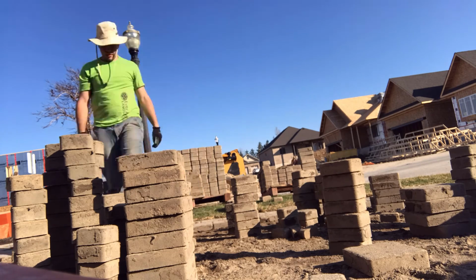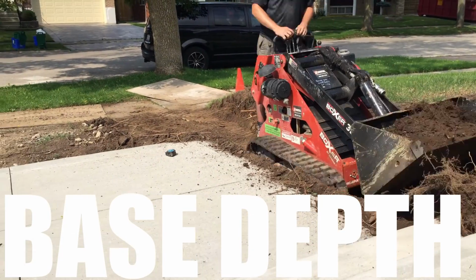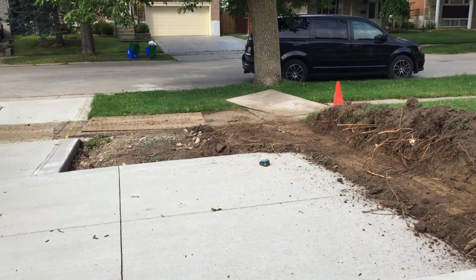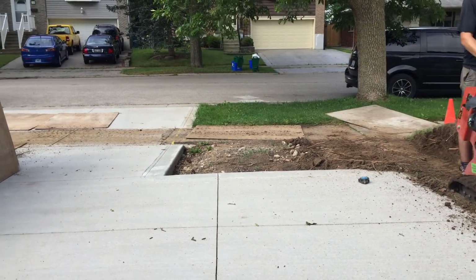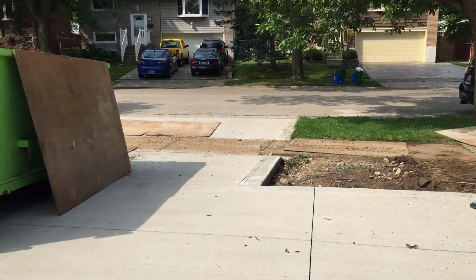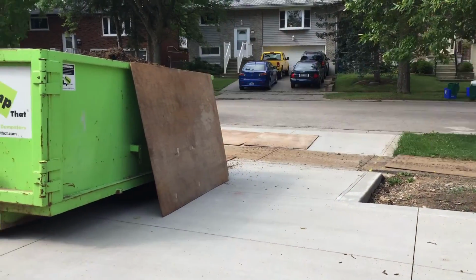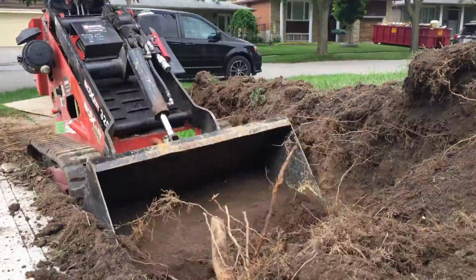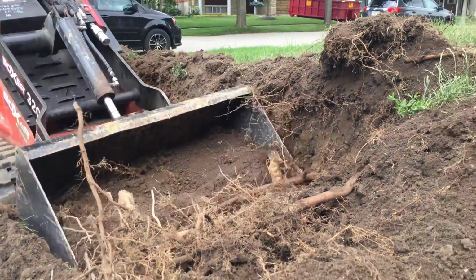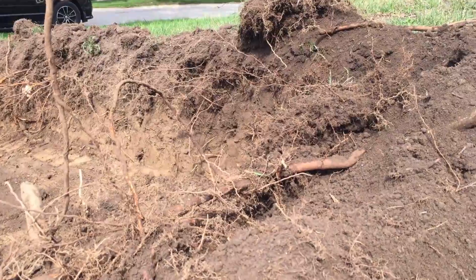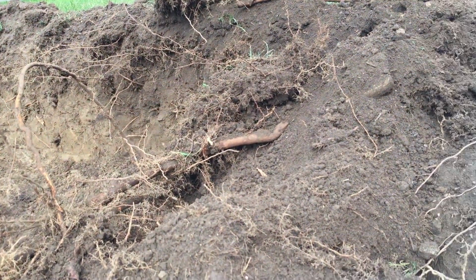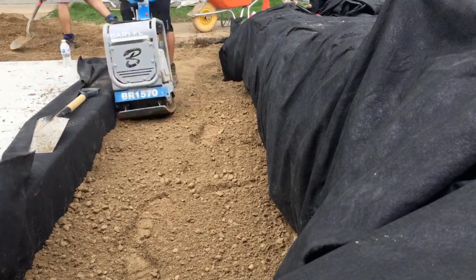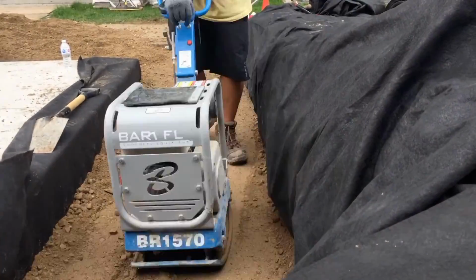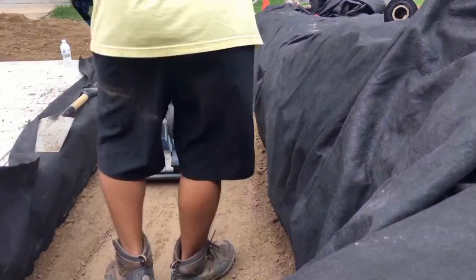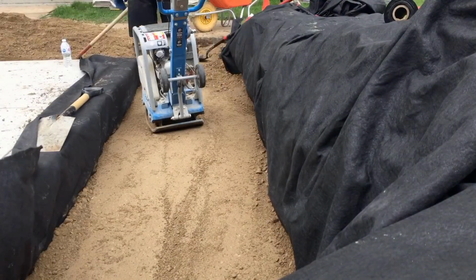which brings me to our second point, and that's the base depth. A lot of projects that I lifted up had inadequate base depth, and that's important when it comes to creating a solid foundation for your project to sit on. There's not much to talk about here really. Just have adequate base depth for the climate that you are in. For example, in Toronto, we have multiple freeze thaw cycles every year in the winter, so we want to make sure we have adequate drainage below our surface, and that means having proper base depth, which for us, I do a minimum of 6 inches for patios to a max of 8 inches typically.